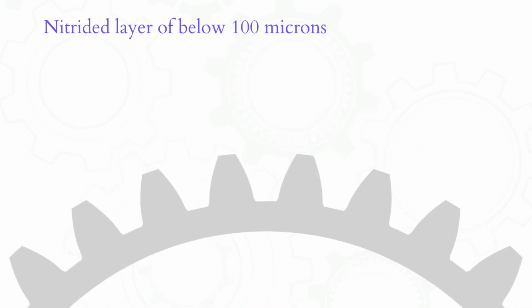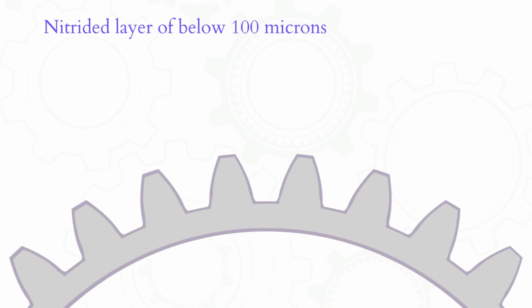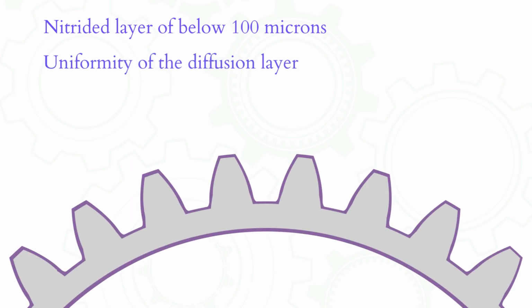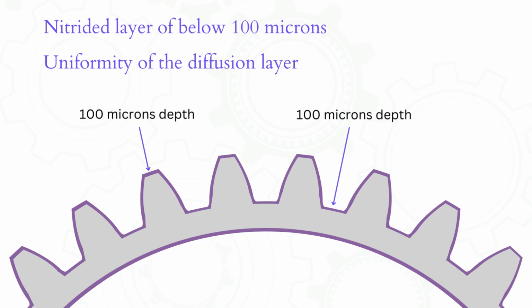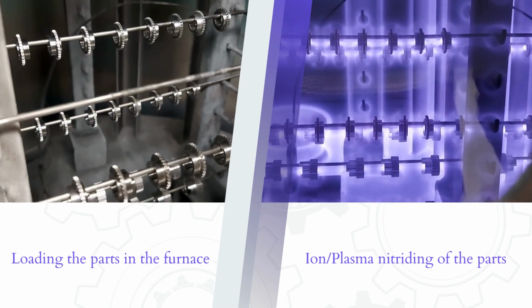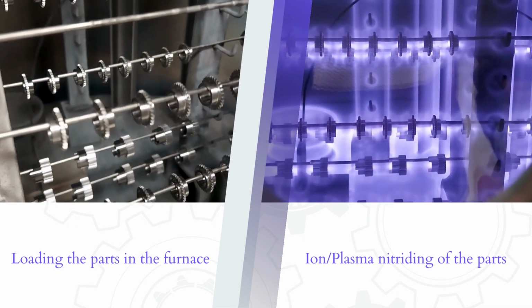Now that we have the surface hardness before nitriding, let us look at the two main challenges that we need to consider. The first one is achieving the requirement of a diffusion layer of below 100 microns. And the second challenge is to have a uniform diffusion layer on top of the tooth, as well as between the gear teeth. This is a challenge because of the very small size of the gears that need to be nitrided. We have carefully arranged the parts into the furnace, and we start the process of ion nitriding.